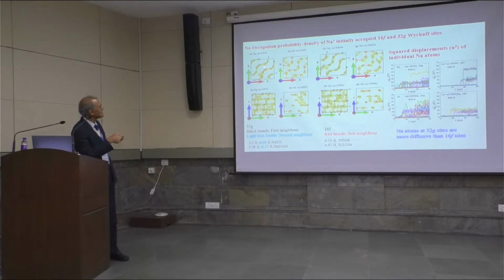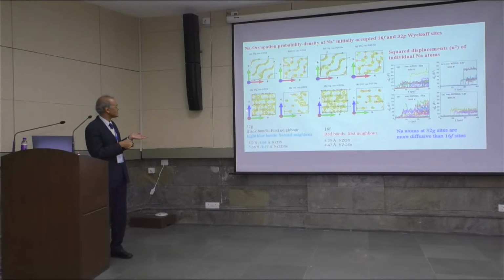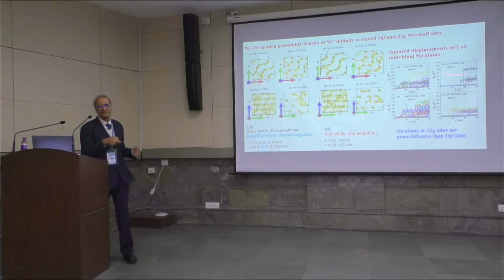enables certain pathways, and these are, you can say, some kind of zigzag chains of the sodium atoms in a plane, and they also have atomic diffusion or jumps across. So this is the AB plane in the crystal structure, and if you project the BC plane, C is along the perpendicular direction. So there are also jumps between the chains along the C direction, and this way we have identified what the pathways are and what the topology of the structure is that helps in the process. So in other materials, if you can identify this kind of topology, that would be helpful.